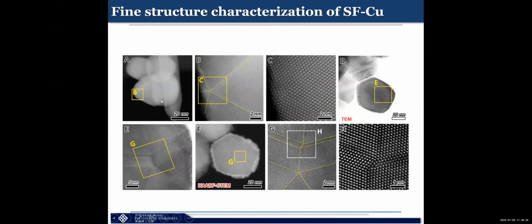And then if we go into even finer structure analysis, atomic-resolution TEM, you can see all this structure. There are different dislocations, boundaries, stacking faults, all these kinds of material features on our catalyst. So later on, we found that this catalyst is very, very good for CO2 reduction with very high selectivity for C2H4.